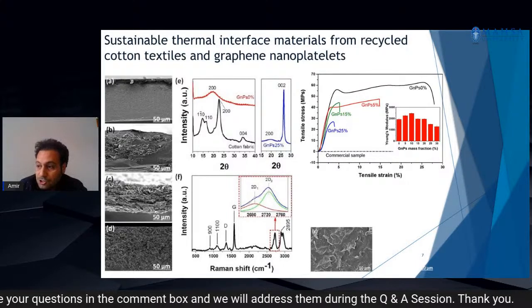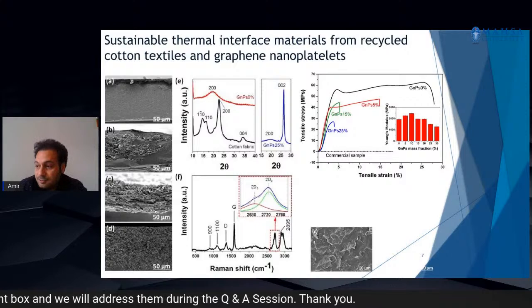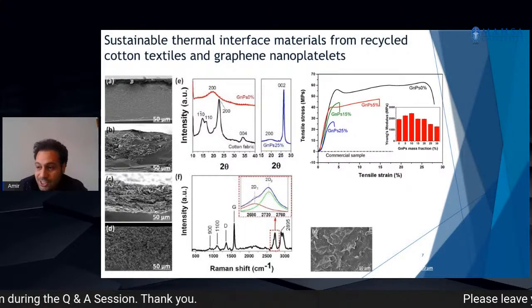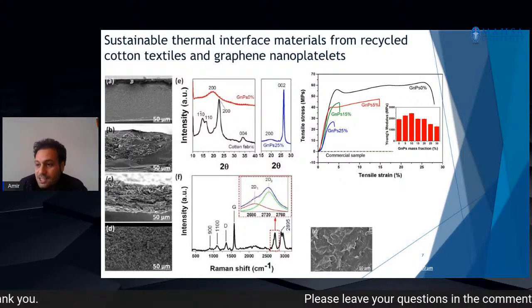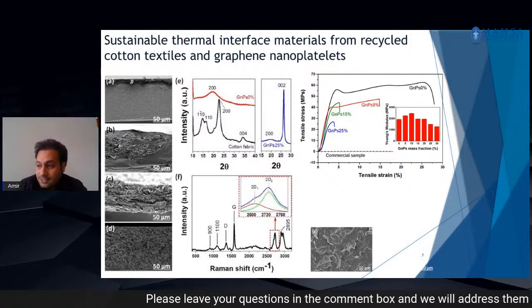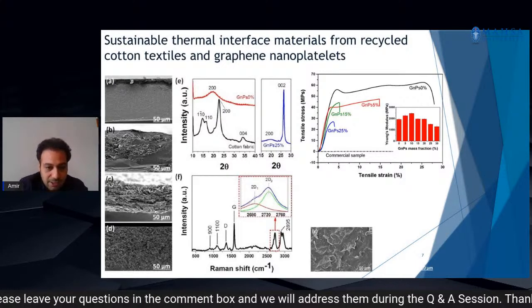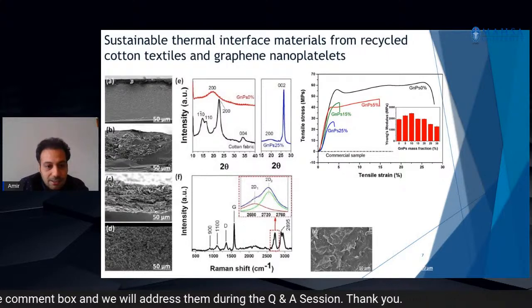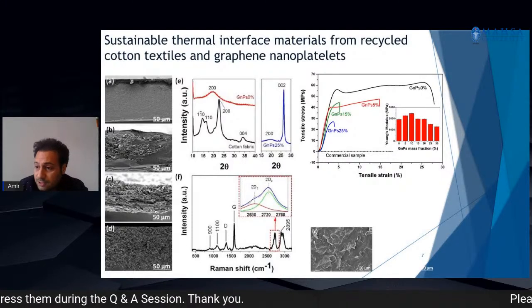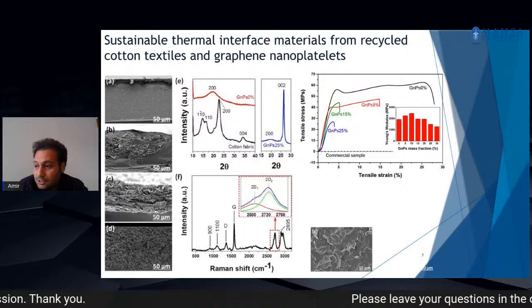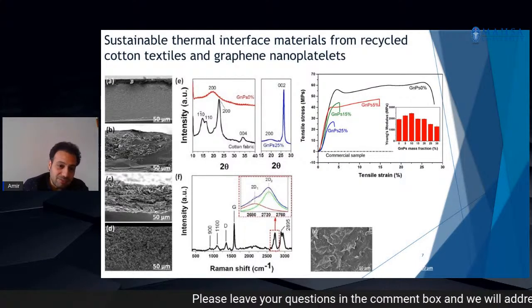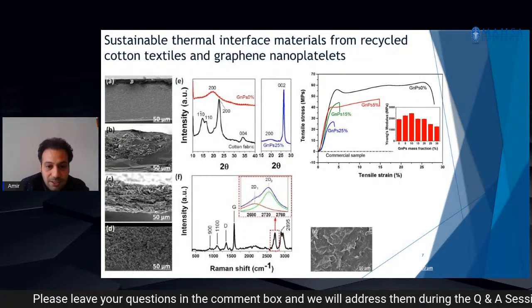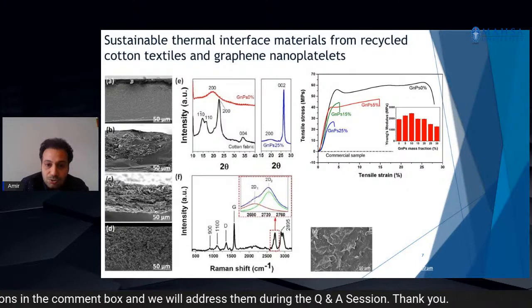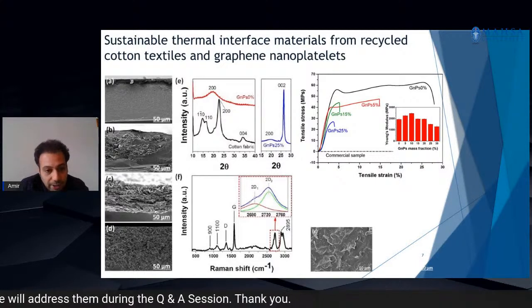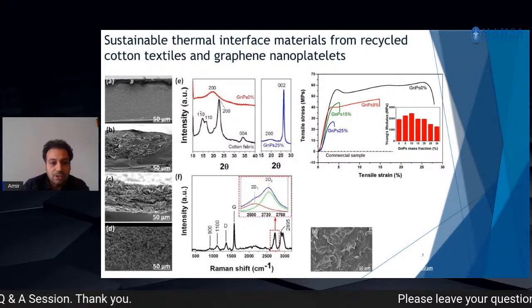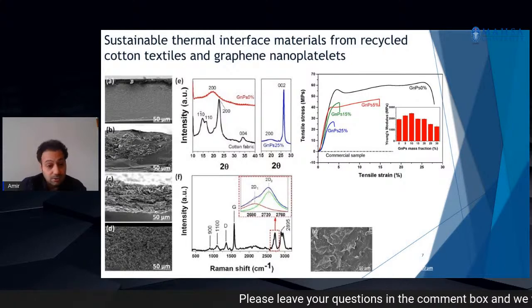The cross-section morphology of the nanocomposite indicates that at a relatively low GNP mass fraction, like 10%, the nanoplatelets are not well in contact, and there are large graphene-free cellulose areas on the surface. So here you can see that by adding the GNPs, we are changing the morphology of the surface. After that, when we load it, we characterize it. You can see in image E, we are using XRD to check exactly the elements on the surface, and also with Raman we again characterize the surface of the sample.